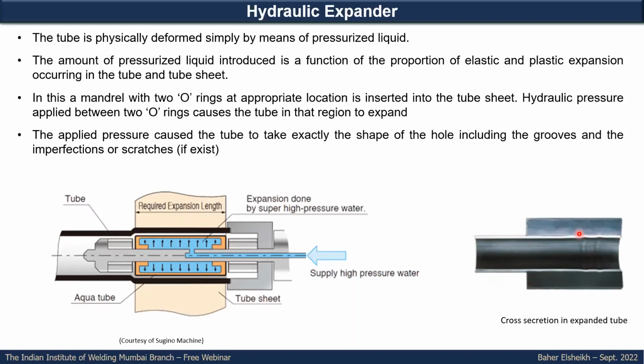This is not usually the case with mechanical rollers, because the mechanical roll will have a little bit longer length, so the groove will come somehow in an area within the roll. So the roll has a maximum OD. It cannot go beyond the maximum OD of the roll itself. But in hydraulic expansion, it is pressure, so the pressure will force the tube to go and somehow do more plastic deformation in the groove. That's why the width of the groove in hydraulic expansion needs to be well respected, like the recommendation of the TEMA and the manufacturer. It has a little bit wider width.